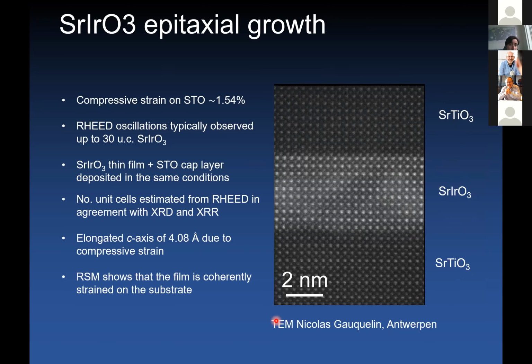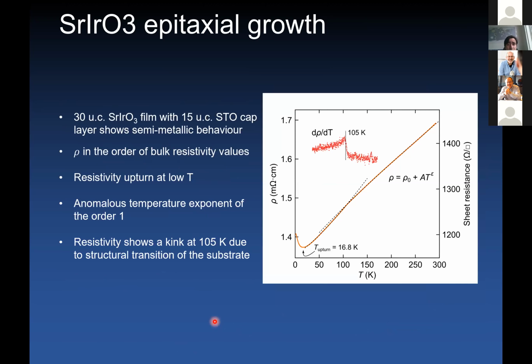And you can see that we can indeed fabricate pretty good films. The transport properties of this semi-metal, this paramagnetic semi-metal system, are quite unusual. So this is a resistance versus temperature curve of a 30 unit cell film. And you see that you have an anomalous temperature evolution with an exponent of the order 1. So this may be interpreted as a sign of correlated behavior of these electrons.